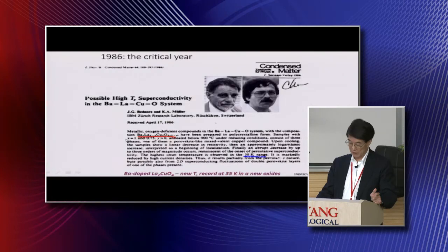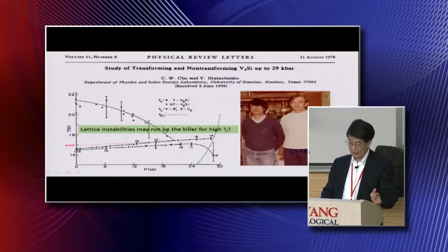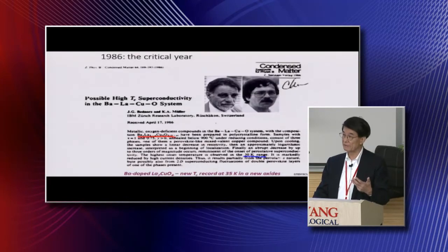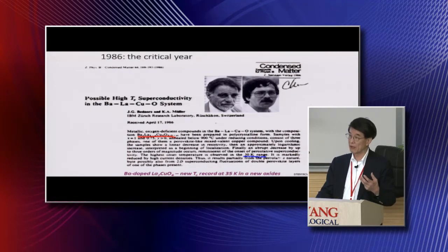So therefore, from this study, we immediately realize that it should not be the killer for higher TC. It only affects transition temperature a few tenths of degrees. It's not the major thing. So that gave us lots of confidence. And therefore, of course, at that time, we were also looking at the oxides.